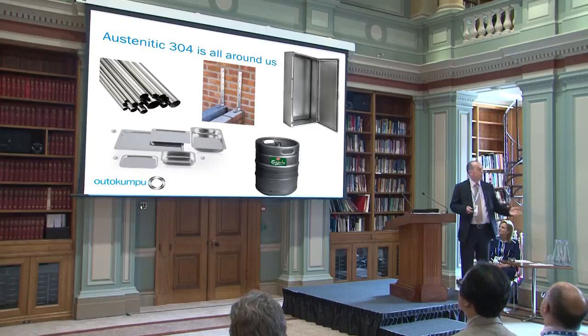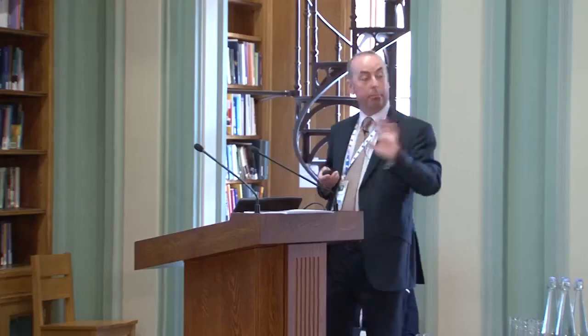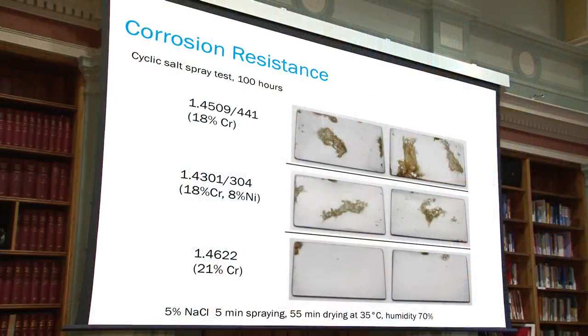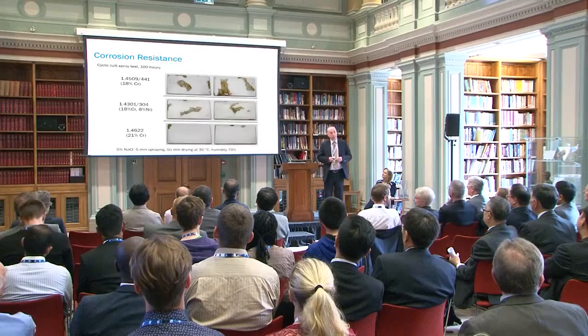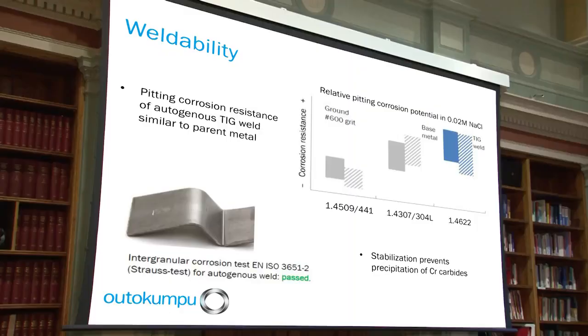Austenitic grade 304 is all around us in everyday applications, but the ferritic 430 grade is an increasingly important competitor in the UK market. Now, with further development, new improved grades of ferritic stainless steel are available, and these have better corrosion resistance and enhanced weldability. Alloying with chromium up to 21% and using titanium and niobium additions of up to 0.7% has enabled the development of a cost-effective and much improved ferritic stainless steel. This is more formable and weldable, with corrosion resistance equivalent to that of austenitic materials, but with the enormous benefit of using no nickel.